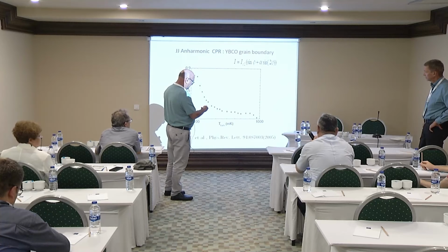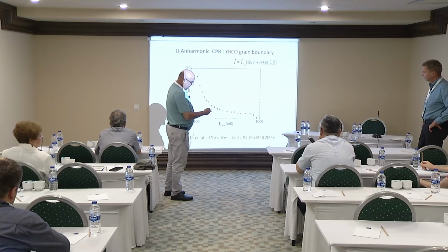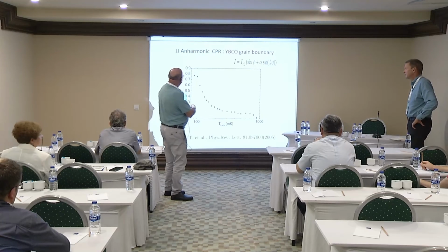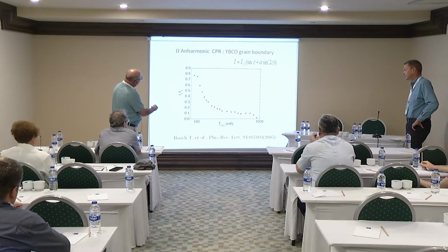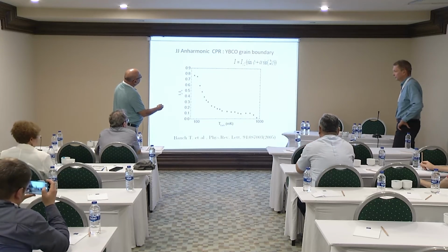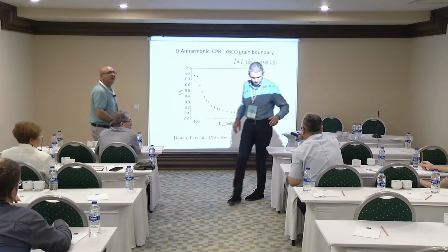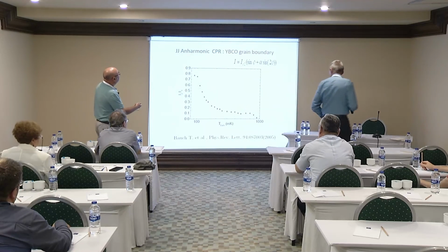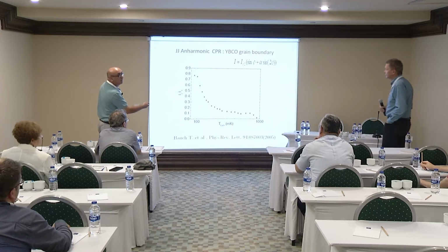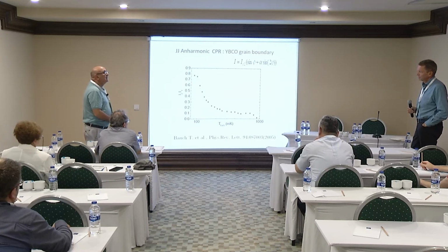Here we also introduce this, sometimes maybe phenomenologically, but there are experimental results which show that at low temperature the second term becomes more important and should be taken into account in the study of qubits based on Josephson junctions, the YBCO grain boundary Josephson junctions.